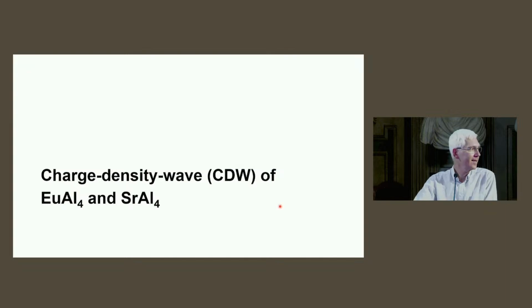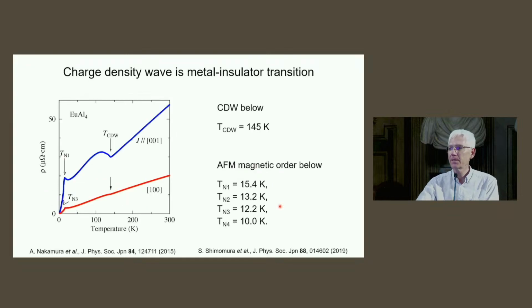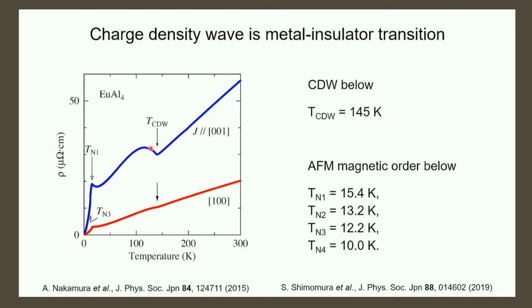So now I come to my last part, if I'm allowed. And that is our recent results on charge density wave compounds, europium aluminum 4, strontium aluminum 4. So this is the europium aluminum 4 compound electrical resistivity as a function of temperature by Nakamura and Shimomura. And you can see it's also very anisotropic along A. There is a small anomaly here, but along C there is a strong anomaly indicating charge-density wave transition, sudden upturn of the resistivity, and here it gets complicated.